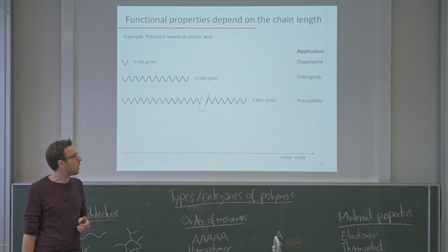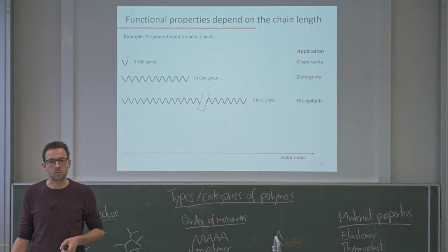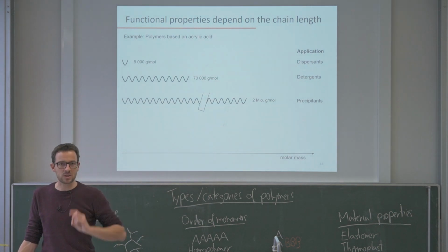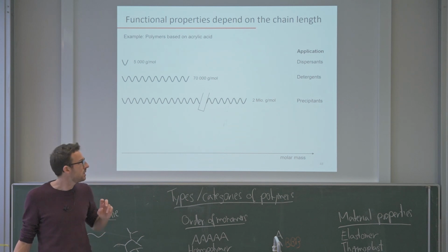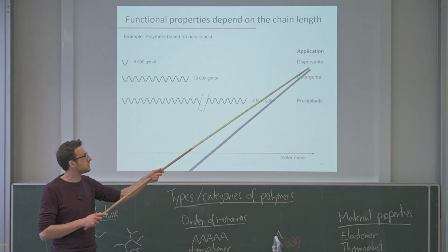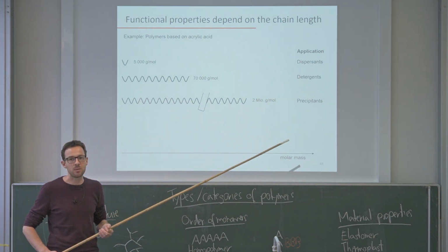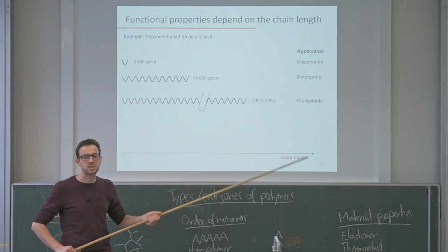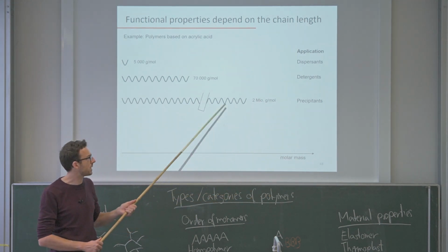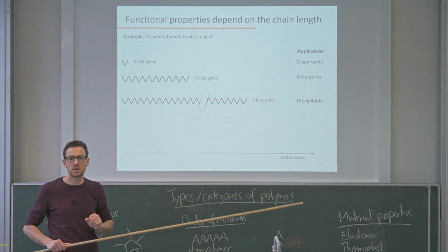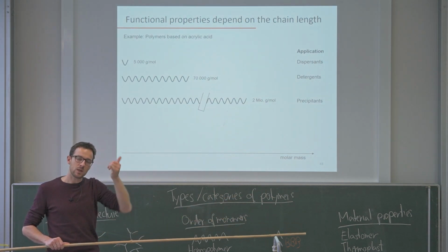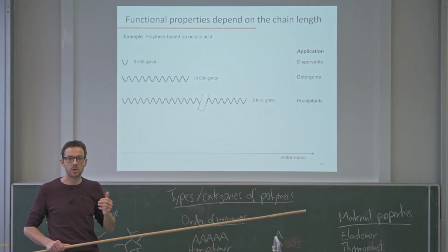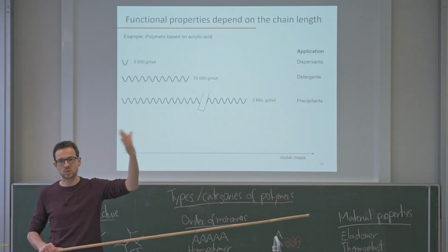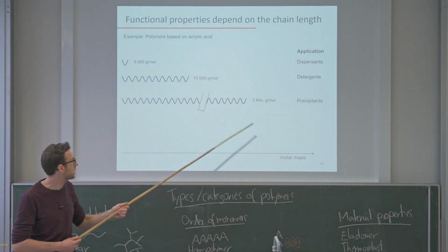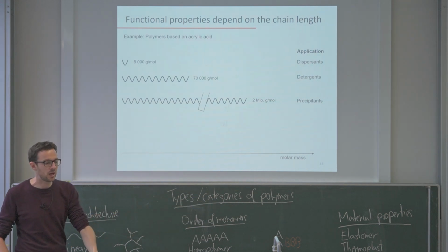Now you make it much longer, let's say 2 million grams per mole, and suddenly the very same polymer, the very same chemistry, instead of being a dispersant that you use to make particles more stable, it becomes a precipitant. So now you add this to particles and they all precipitate. So it really diametrically changes its properties from something that helps stabilizing to something that destroys stabilization, simply by the different chain length. And why is also clear.